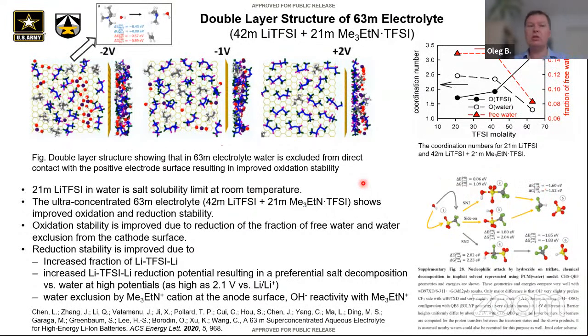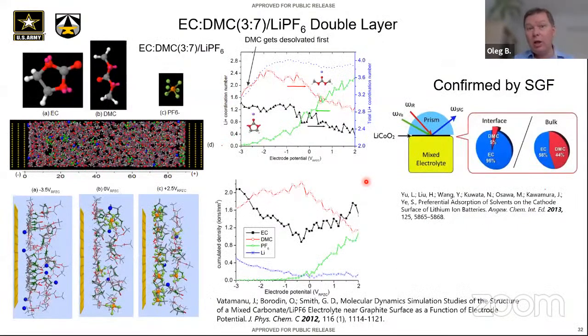So that leads us to a little bit more understanding of how the double layer can play a multifaceted role in terms of stabilization of SEI at different reduction potentials. It also plays a role in water-in-salt electrolytes, which are heavily concentrated, and because of that lack of free solvent, there is this expulsion of solvent at high potentials.